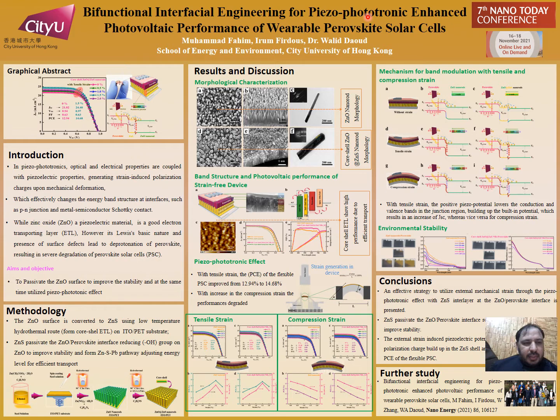However, zinc oxide has an alkaline nature, and the presence of surface defects leads to the deprotonation of the perovskite, which causes severe degradation of the perovskite solar cell.